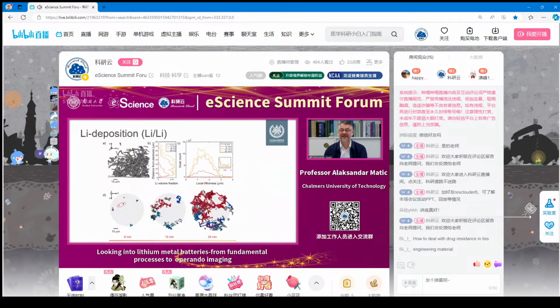So we analyze the thickness of all the structures formed in the volume, and you can see here that already after 12 minutes of deposition, you have structures which are somewhere between 1 and 2 microns in thickness on average, and this average stays the same throughout deposition. So this shows that the structures will grow in size, but not actually in thickness.